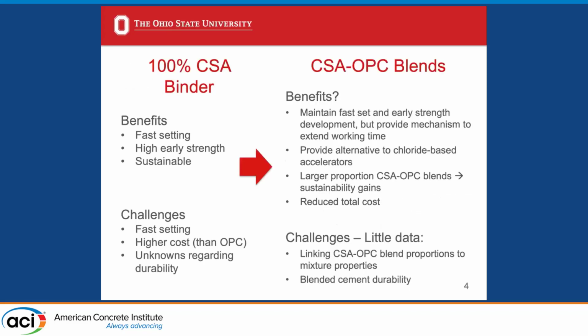So our hypothesis was that perhaps we could address some of these concerns through the use of a CSA OPC blend. So our idea is to maintain that fast setting time and early strength development, but use the OPC to dilute the system and enable us to extend our working time.